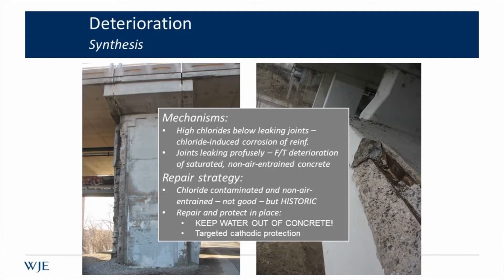But then we also needed to be mindful of areas of sound concrete, again, that were chloride contaminated, and because it's 1923 concrete, it was not air entrained. Air entrainment wasn't used until the 30s, so all of this concrete and all of the reinforcing steel in it, the chloride levels were high enough, and the absence of air entrainment created a risk that we could walk away from the bridge and not prevent damage from developing in some of these adjacent areas in a short amount of time. So the goal was to keep water out of the concrete and then employ targeted cathodic protection where warranted.